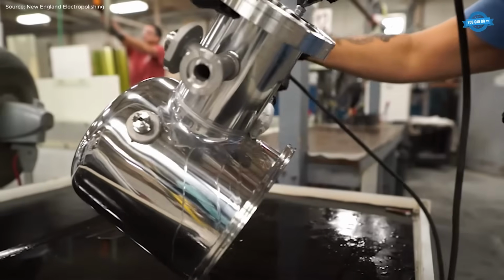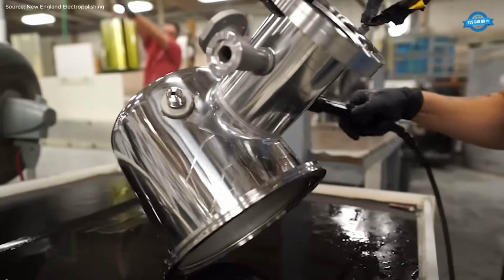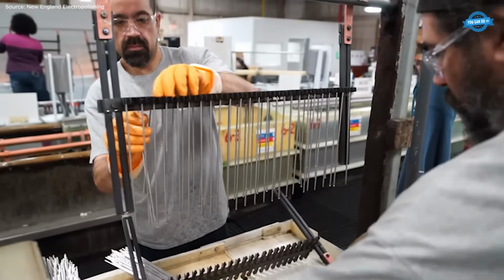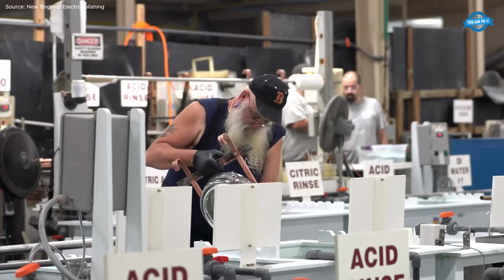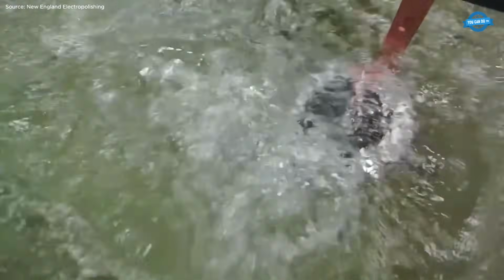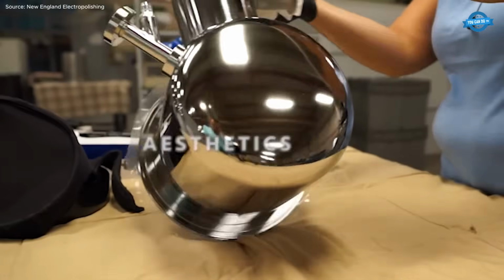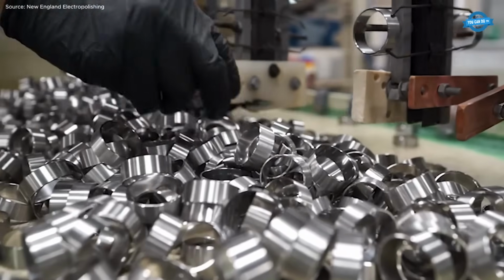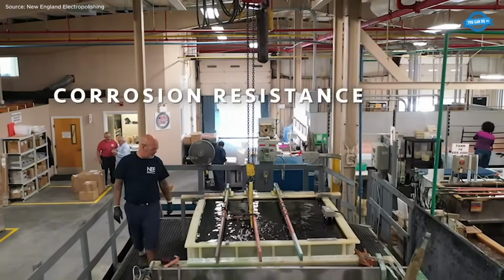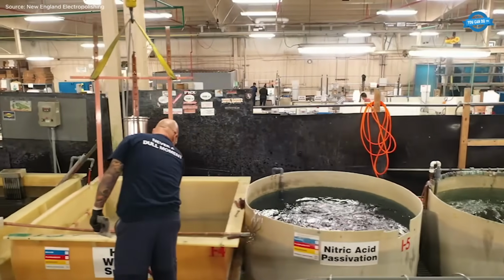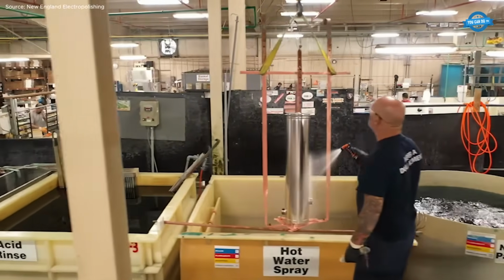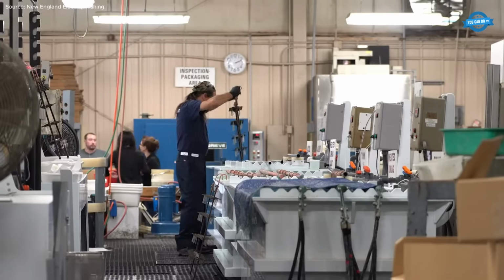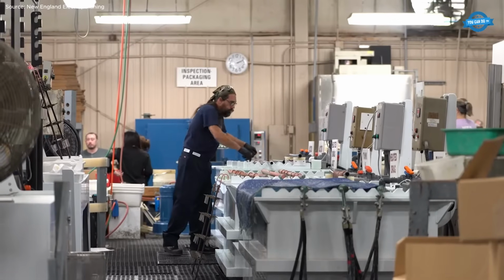Electropolishing transforms metal at a microscopic level, dissolving peaks while leaving valleys intact, to create an ultra-smooth, mirror-like finish. Beyond aesthetics, the process removes embedded contaminants, enhances corrosion resistance, and reduces friction, making components easier to clean and longer lasting. Properly controlled parameters can also achieve passivation, forming a protective oxide layer without mechanical abrasion.